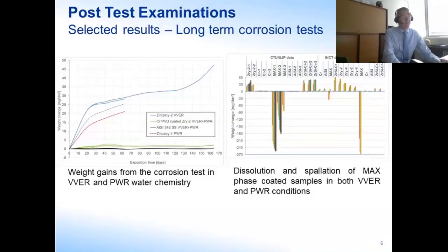And sometimes, as it was with MAX phase coatings, you can see that a very strong spallation effect was observed. So eventually there was no gain, but loss of material. For this reason, you cannot see it in the left graph. Relatively good behavior for the steel samples, but the best, of course, you can see, are chromium coated samples.